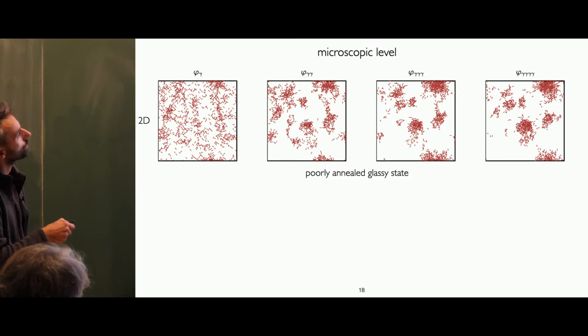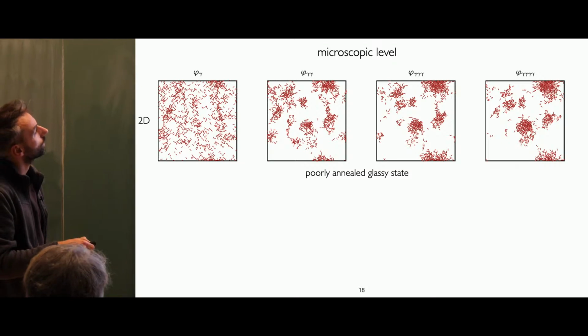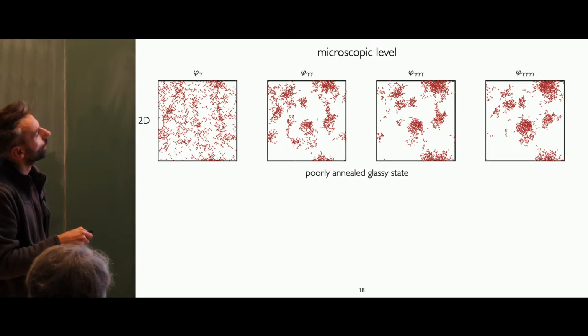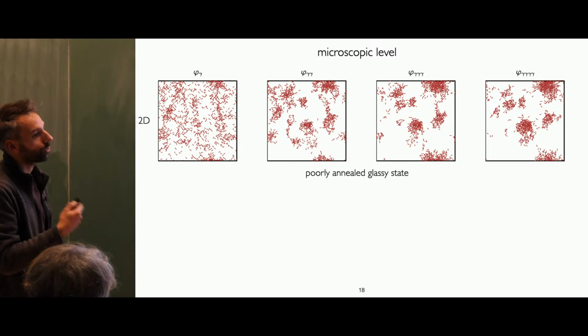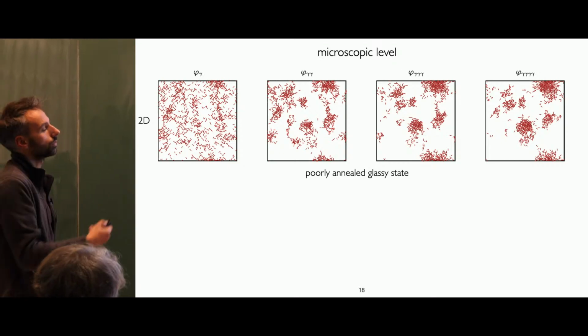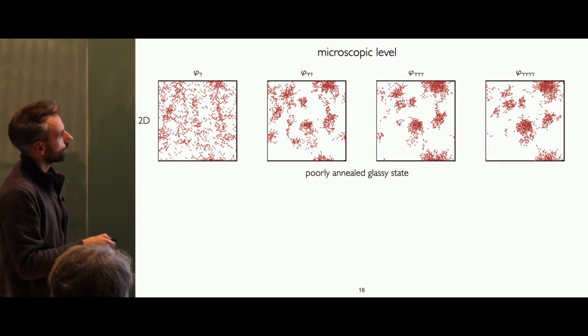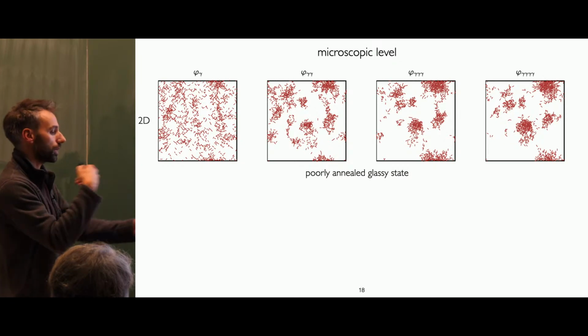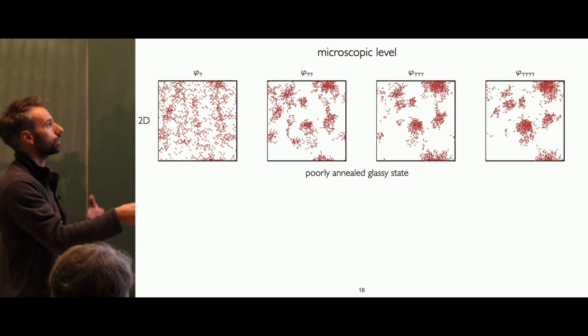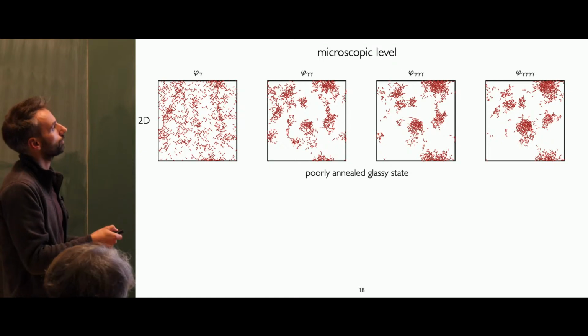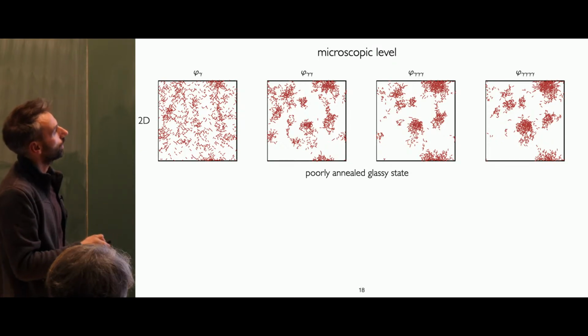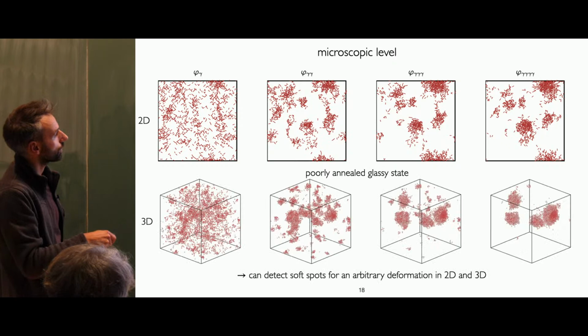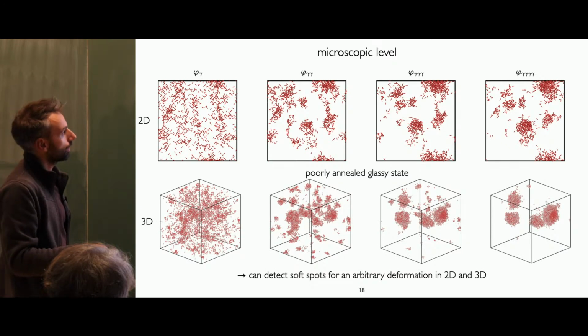And when you start to take higher nonlinear terms, you can pick up what are the soft spots in your system that couple the best to the imposed deformation that you use as an entry. So that gives you a map for a particular deformation. So you could repeat this for other types of deformation. So that's really a tensorial map. And you can do this in 2D, but you can also easily do it in 3D.